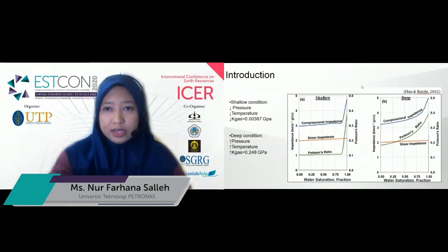This is the study conducted by Han and Batzle in 2002 to explain the difference of rock impedance reduction with the presence of gas in shallow and deep sections. In the shallow section, there is lower pressure and temperature, so the gas trap is likely to have a gas phase behavior with very low gas modulus, around 0.00387 gigapascal. On the left figure, we can see a drastic drop of rock impedance from 0 to 10% of gas.